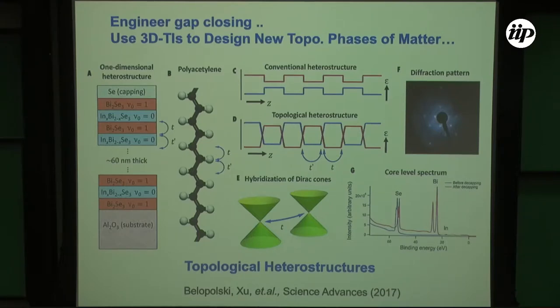Experimentally, what we do is cap these materials with selenium, then transfer to a spectroscopy chamber, an XPS chamber for example, and then we decap it. How do we know? Why should you believe us that we're not looking at the selenium layer, but that we want to look at this layer?